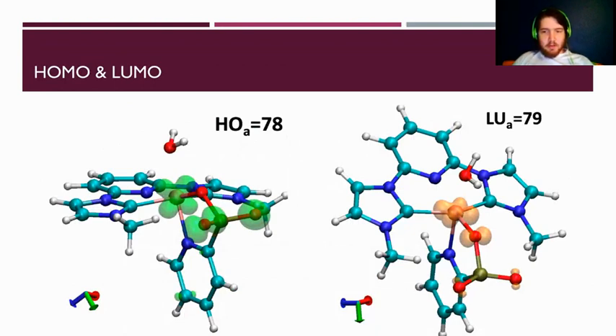So looking here, we have a visualization of the HOMO and LUMO of the ligand. And what we can see here is that they are primarily centered around the ruthenium atom and the oxygens of the phosphite group that's attached onto one of the organic portions of the ligand. And so this is interesting, in that it's very likely some sort of hybridization is possibly happening.